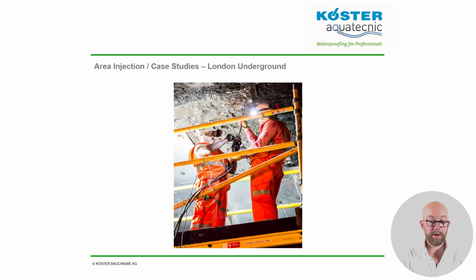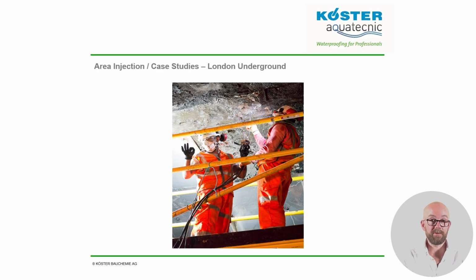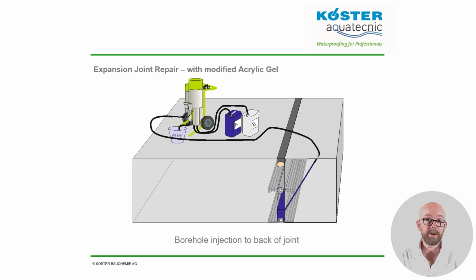The packers were then re-injected one at a time in the grid pattern. Each packer was injected 3 times, but by the third pass, very little gel was entering the borehole and the dripping water had stopped. After 48 hours, the trial area had dried up completely, whereas the surrounding brickwork was still heavily leaking. Continuing with acrylic gels, we now turn our attention to expansion joints.